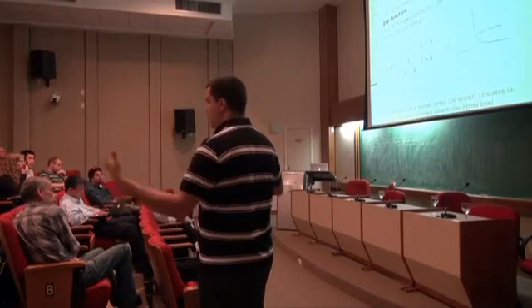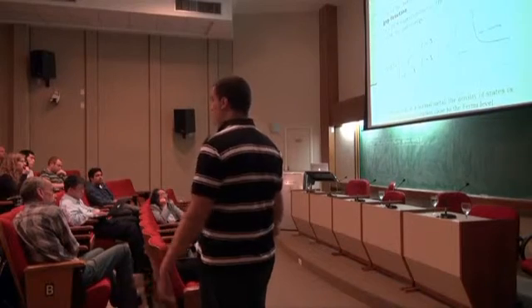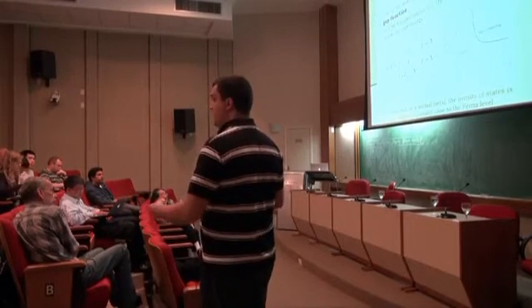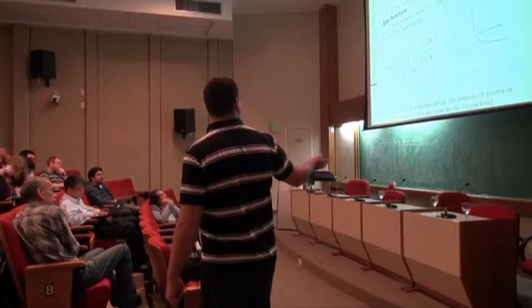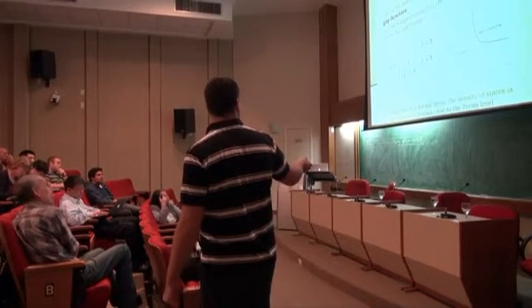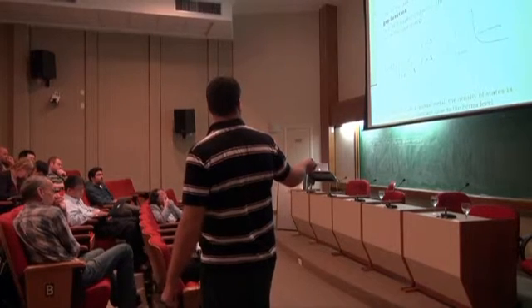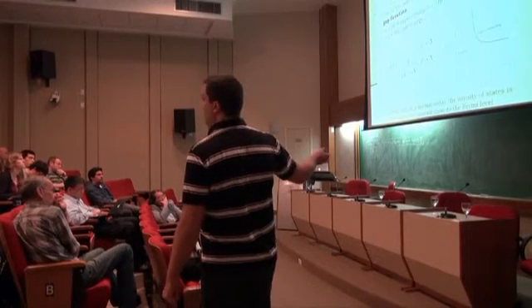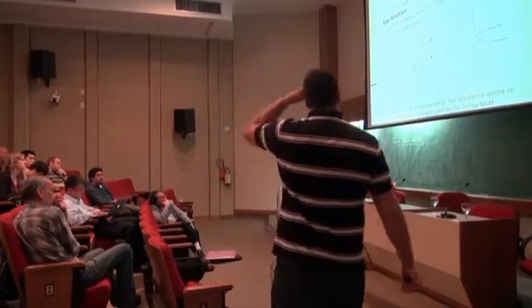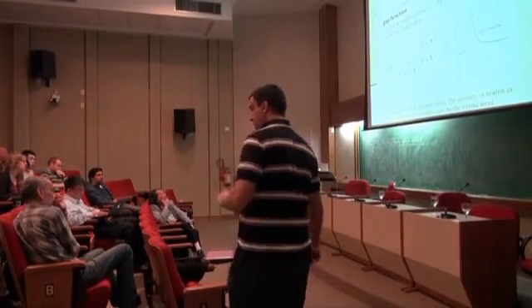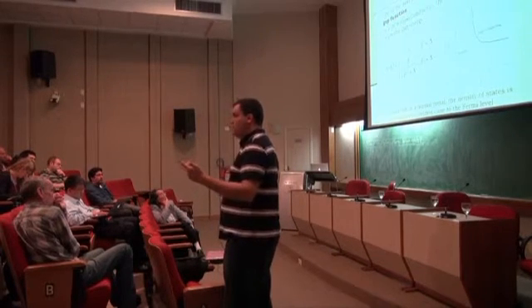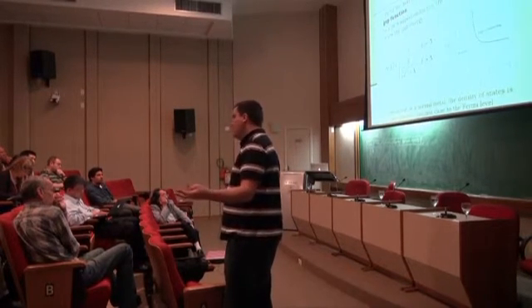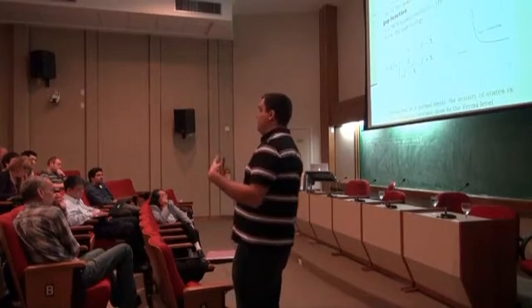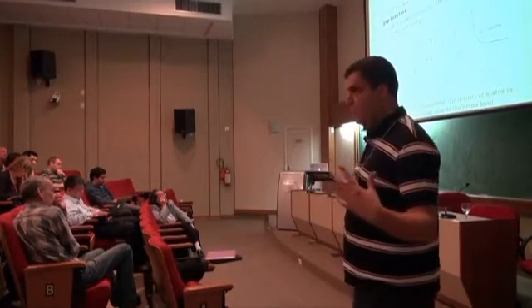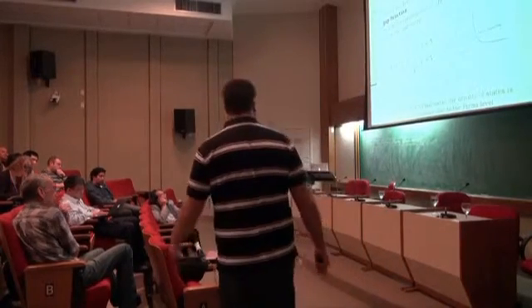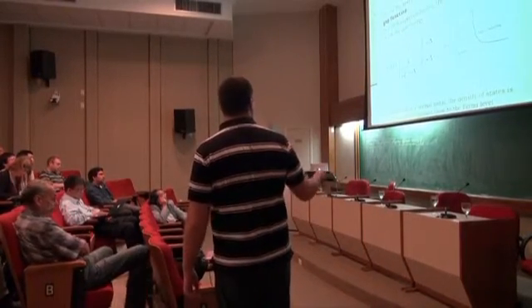In a superconductor, where you have all these Cooper pairs forming a new state, the density of states, which was a constant, as this dashed line shows here near the Fermi level, is gapped, meaning that I find no states until the energy delta, then I find a peak and a decay. So this quantity, the gap function, is very important to understand superconductivity. And that was one of the clues that BCS was right, because the gap was found even before BCS by specific heat measurements or by optical conductivity measurements. But unfortunately, I don't want to go into too many details. So this is a main property.